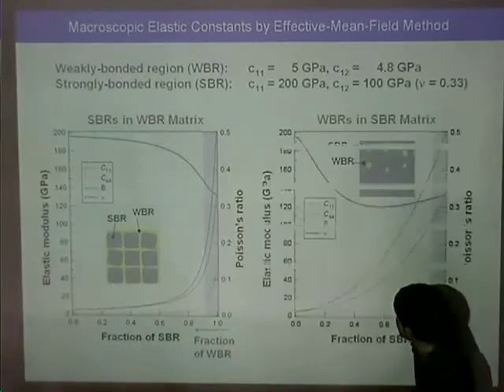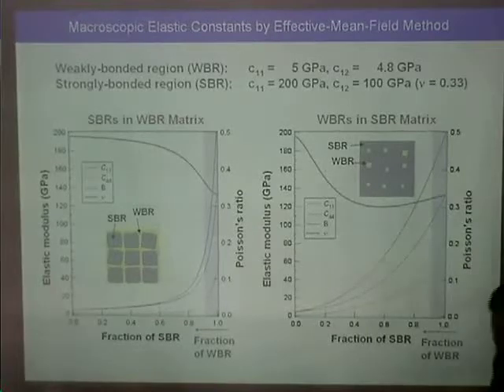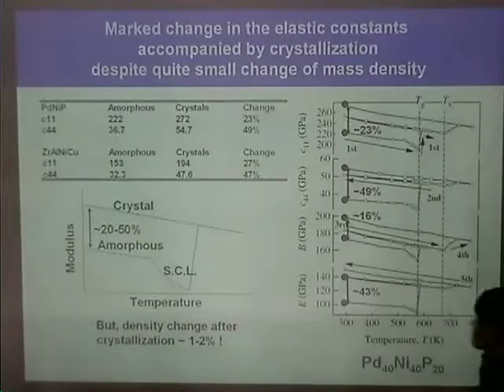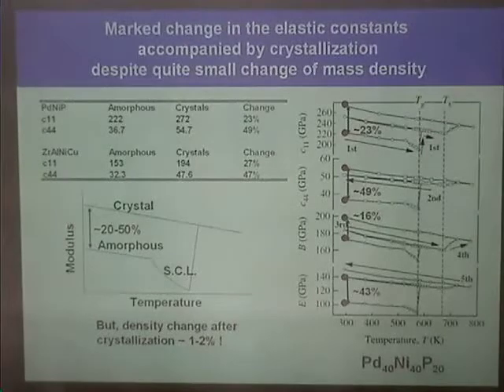I'm sorry, maybe this is a silly way of thinking, but could you back up a slide? So you're arguing that there's something unusual going on because we get such a large change in elastic properties with a small change in density. But that's not unusual. Think of an elemental metal: I can change its volume by 5% and change its elastic properties by 100%, and I'm thinking about melting. If you take pure elemental metal and melt it, you increase its volume by about 4 to 6%, but its elastic properties go to 0. So is this really unusual, that you get a 20% change in elastic properties for a 2% change? Am I looking at this wrong somehow?